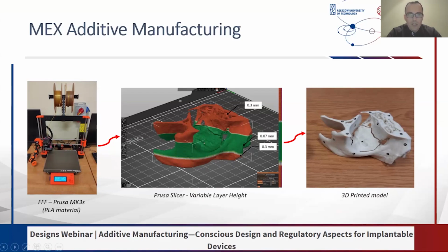So we choose a variable layer height to create one region that is not of interest for the final 3D bending of the titanium mesh. So it is this area and this area. The layer thickness in this area was 0.3, and then most important for us, this area marked by green color, we choose the option of the highest resolution of layer thickness, 0.07 millimeters. So the final representation of the 3D printed model looks like this.